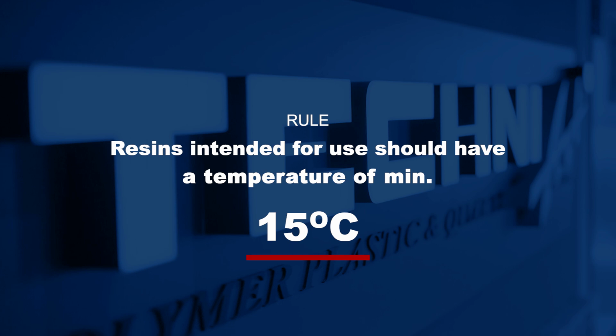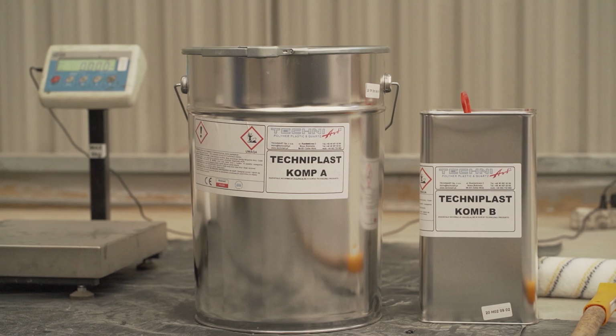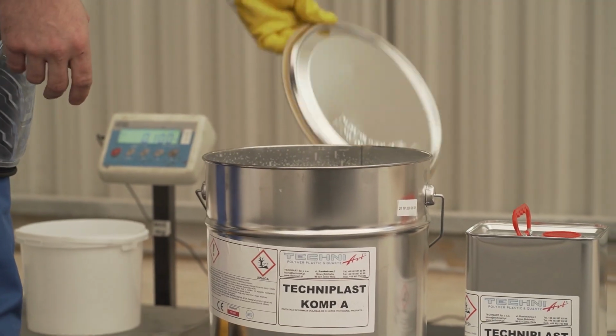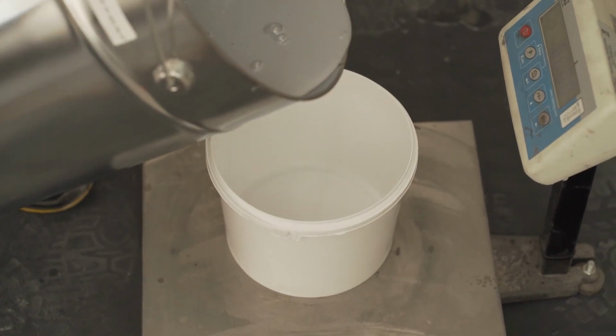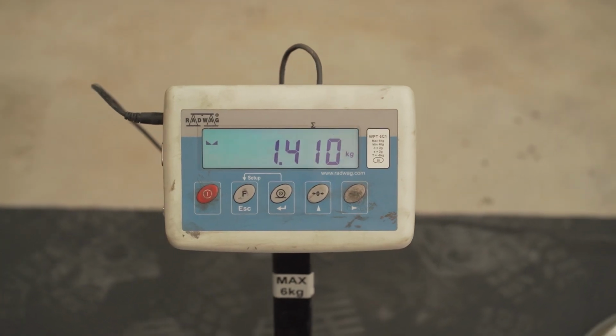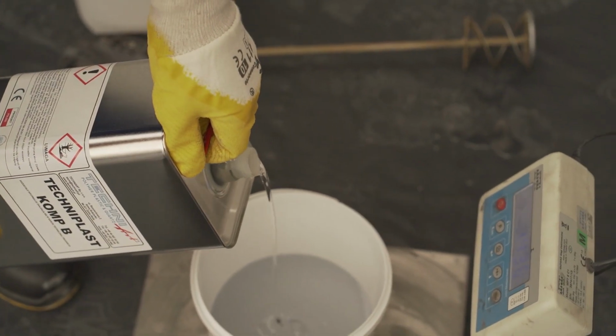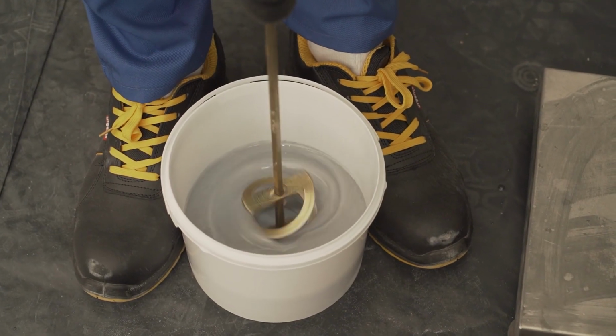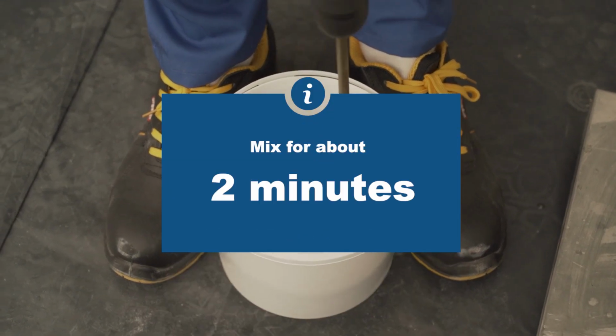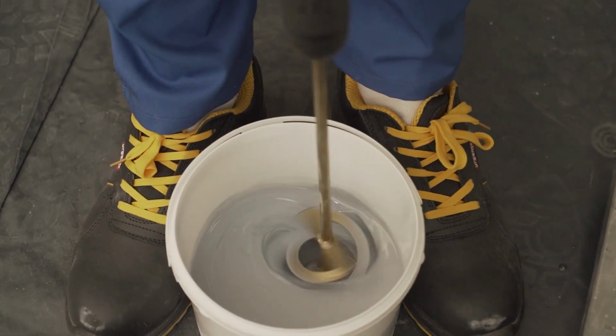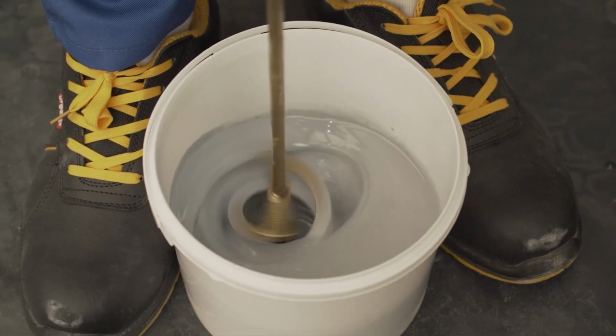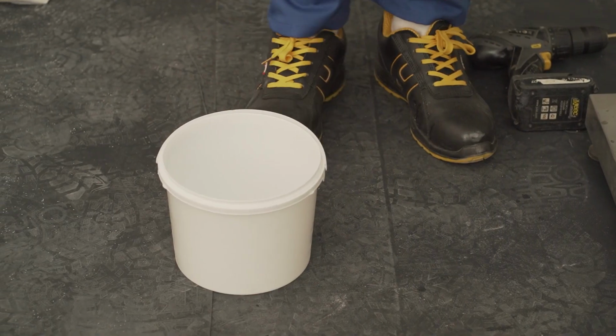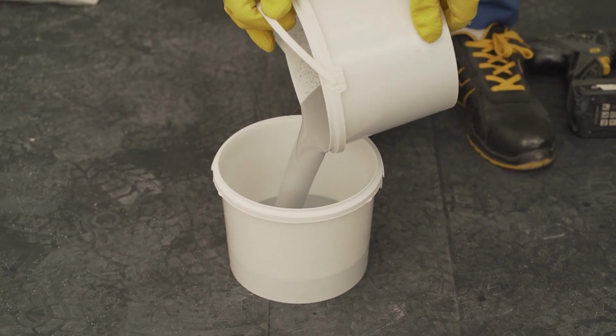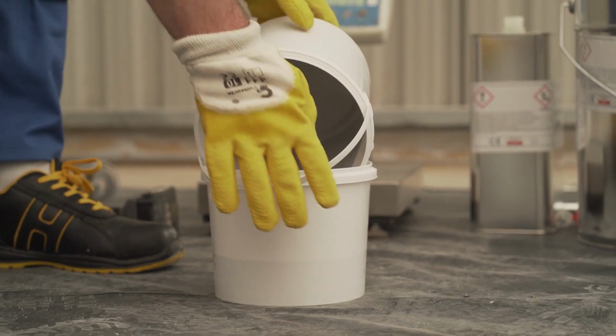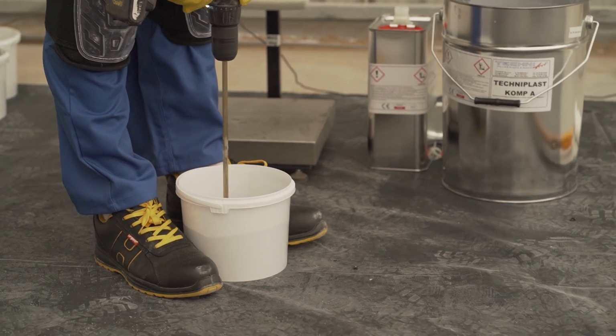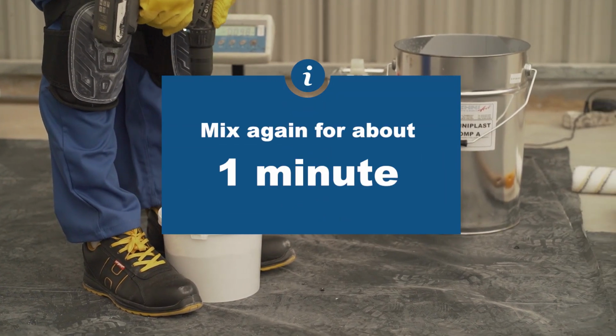Rule: resins intended for use should have a temperature of minimum 15 degrees Celsius. Component A should be carefully weighed, then component B should be weighed, in accordance with the proportion given on the package. Mix with a low-speed mixer, for about 2 minutes. In order to avoid excessive aeration of the material, it is recommended to use a stirrer with a speed of about 300 revolutions per minute. Pour the material into a clean container and mix again, for about 1 minute.